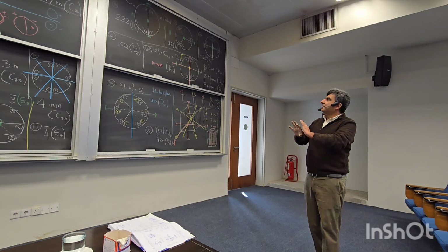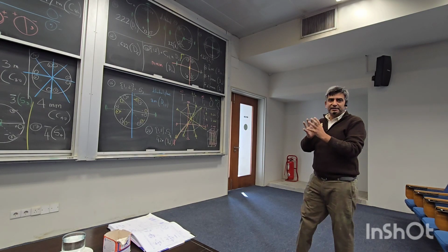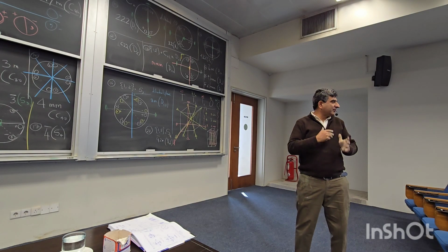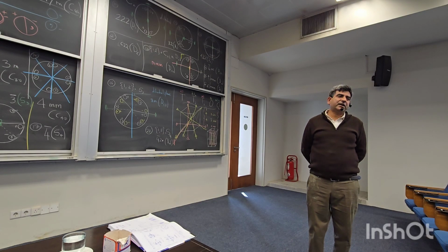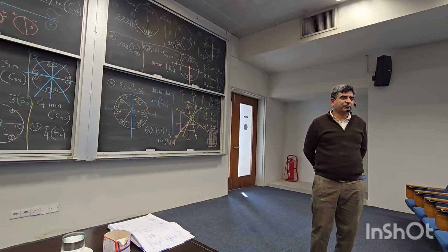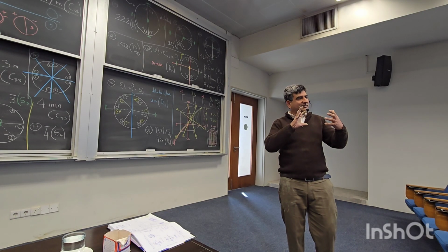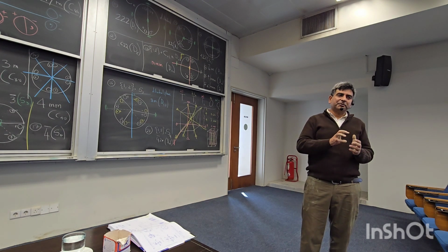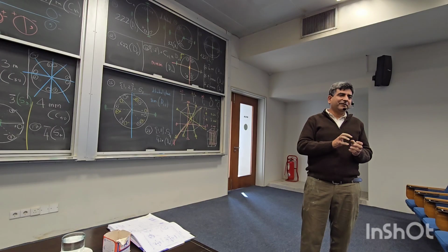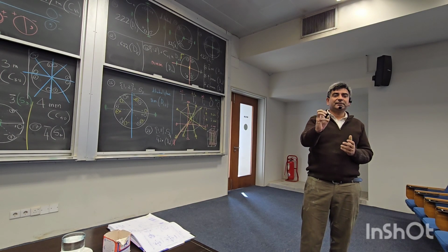So now we can break up, in fact simplify, these 32 point groups and lump together certain point groups which have commonality. For example, all the point groups that have a 4-fold axis of rotation or a 4-bar axis of rotation, they can be lumped together in one set. That set will give you a crystal class. That is a tetragonal crystal system.